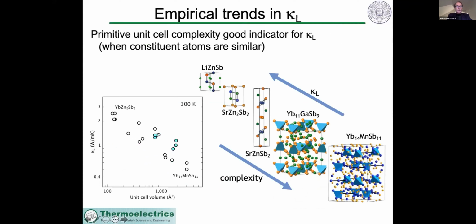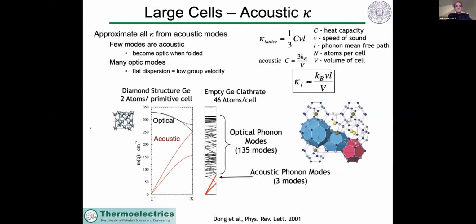So what initiated my interest in complex materials was the fact that the lattice thermal conductivity, which is so important for thermoelectrics, decreases dramatically when the complexity of the unit cell is increased. And so these are examples of very large complex materials where the complexity is measured by the size of the unit cell. And you can see that some of these materials with very large unit cells have very low thermal conductivity, and that makes them great thermoelectric materials.